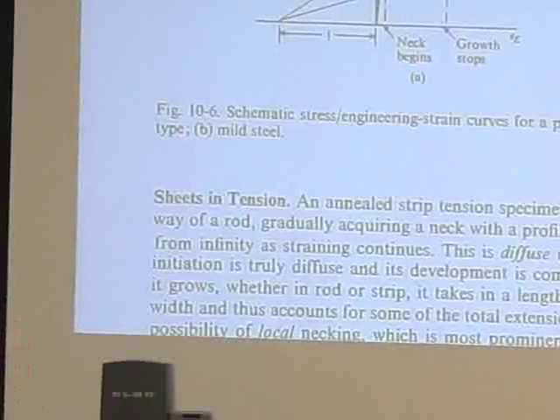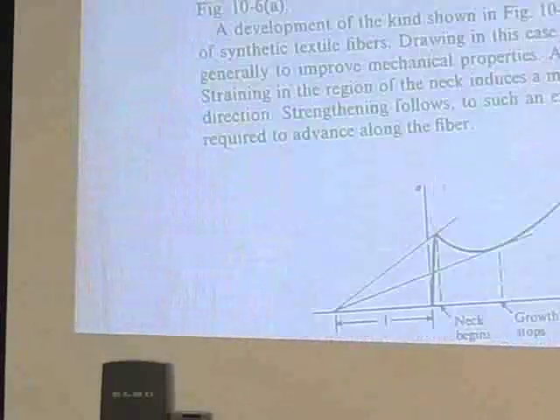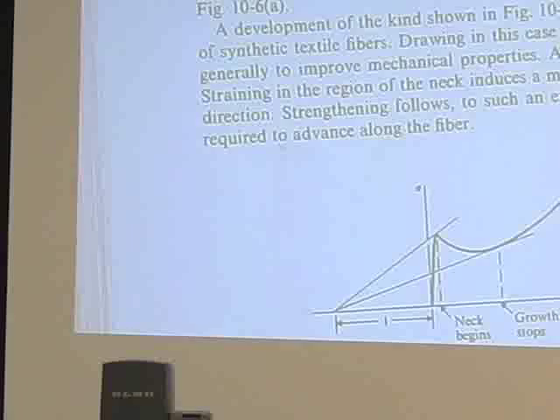Well, if you get the nitrogen out of the steel, which we now know how to do when you melt the steel, you don't get Luders strains. You don't get a stress-strain curve that has this upper yield strength and lower yield strength. It just goes up nice and uniformly, and you end up getting a piece of sheet metal that you can sell. Okay? There's actually nothing wrong other than aesthetically.